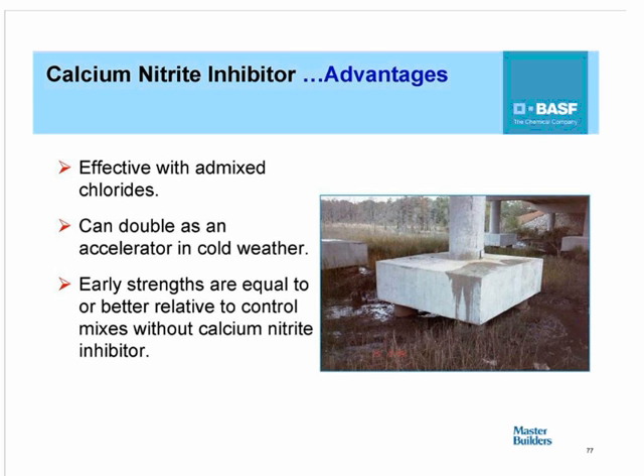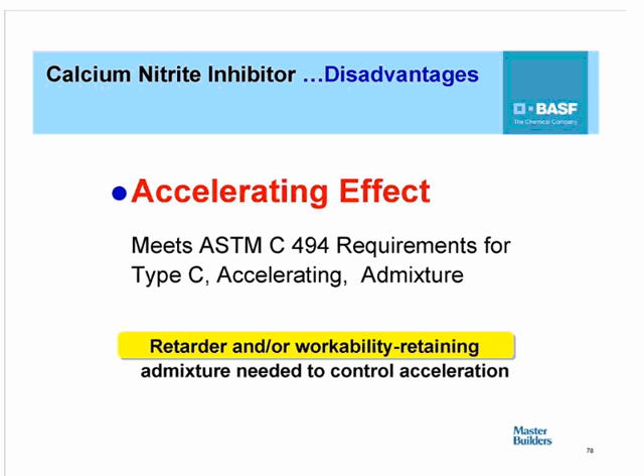And for the most part, in my experience, calcium nitrite inhibitors typically provide compressive strengths that are either equal to or better than the mixes without calcium nitrite. I did mention that it does accelerate. Now, that can be a disadvantage as well, especially if you're concreting in the summertime when temperatures are high. And as a result of that, calcium nitrite inhibitors are typically used with a retarding admixture. And since the introduction of the workability retaining admixture, we found that it also helps significantly in controlling the accelerating effect of calcium nitrite.